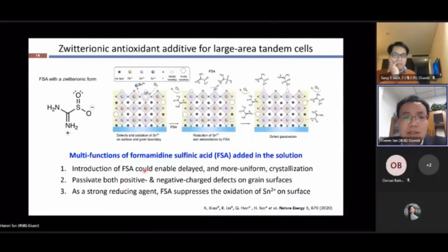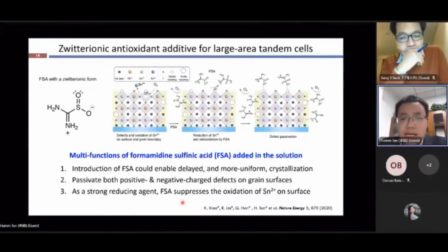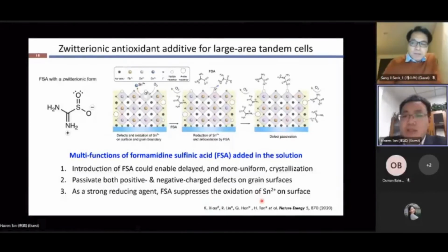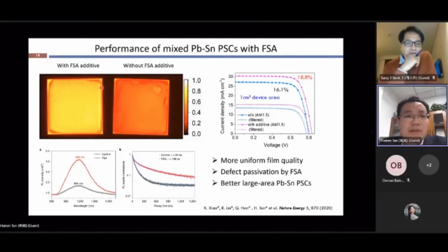And also the zwitterionic functional groups can passivate the positive and also the negative charged defects on the grain surfaces. And also the sulfinic group is a strong reducing agent. It has the ability to suppress the oxidation of tin on the grain surfaces. From the PL mapping of the samples, we can see that after introducing the additive, due to the surface passivation, the emission is brighter, and also the charge carrier lifetime is increased. And we can see from the emission that it becomes more uniform.